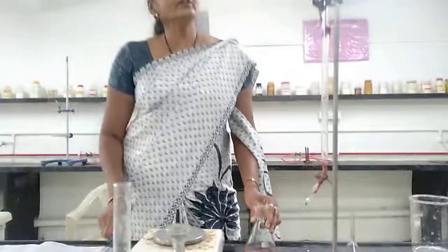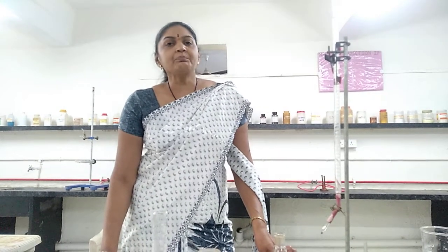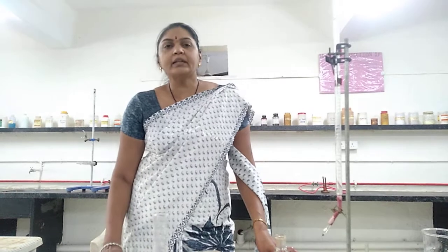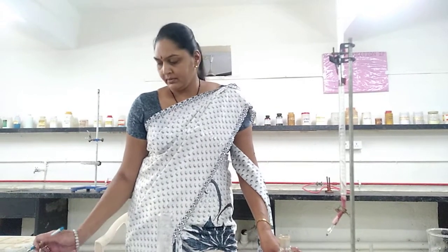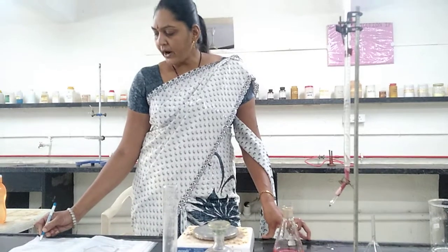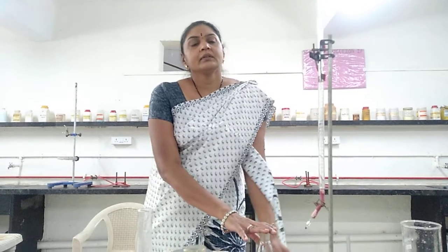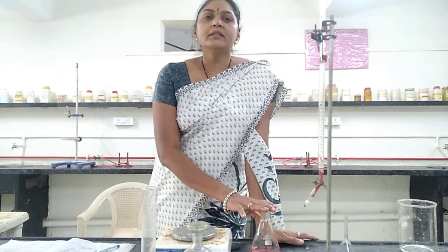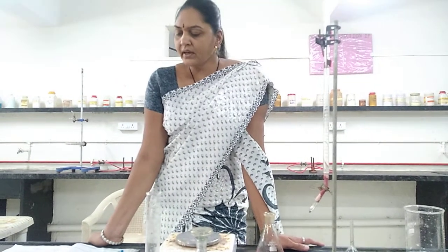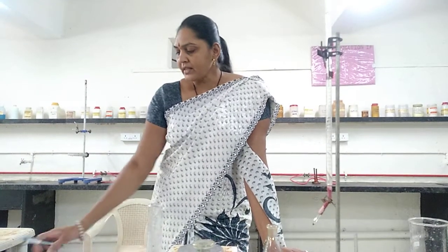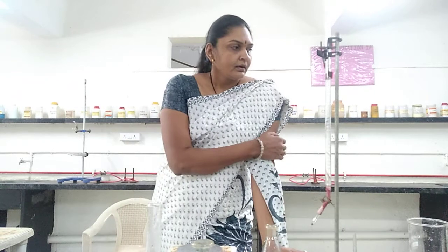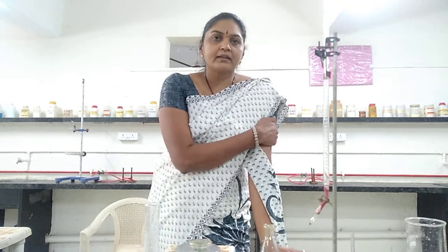The difference between two readings shows the amount of alkali that is leached from the glass. The IP states that it should not be more than 0.02 ml. That is the maximum quantity of alkali that is leached from the glass. The difference between the blank and the extract should not be more than 0.02 ml. This is the hydrolytic resistance glass test.